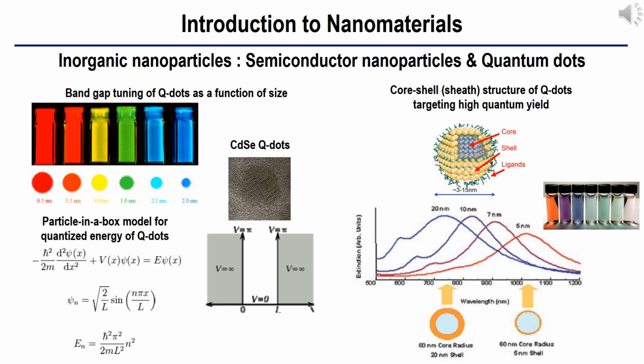This means that you can control the absorption energy from ultraviolet to near-infrared, not to mention the entire spectrum of visible light. For example, cadmium selenide quantum dots with size from 2 to 6.5 nanometers can cover the entire visible spectrum as shown in these color figures. Due to the properties of broadband absorption of quantum dots, they can be good light sources with sharp emission with 20-30 nanometers peak width. However, single quantum dots have a severe problem, which is relatively low quantum efficiency.